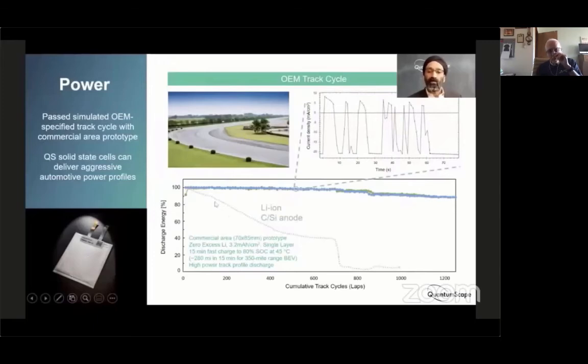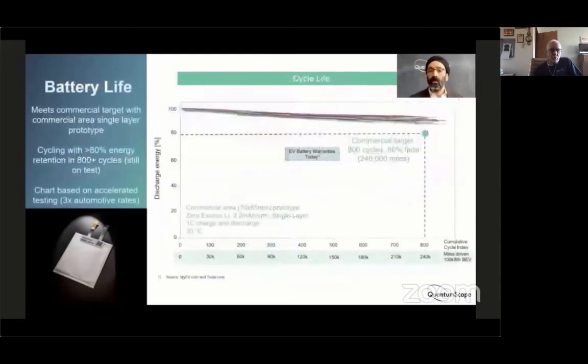Now, what you see with this aggressive test is that the cell goes well over 1,000 laps, which corresponds to more than 100 cycles of charge, discharge at these aggressive conditions with minimal degradation of capacity. By contrast, today's best lithium-ion cells start degrading within a few tens of cycles. So again, this result is really remarkable. Not only is it better than any previous solid-state result, but it actually blows away even today's best lithium-ion technologies. So a super exciting result that demonstrates the robustness of the QuantumScape solid-state technology.